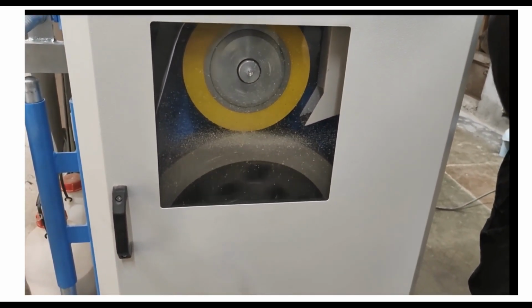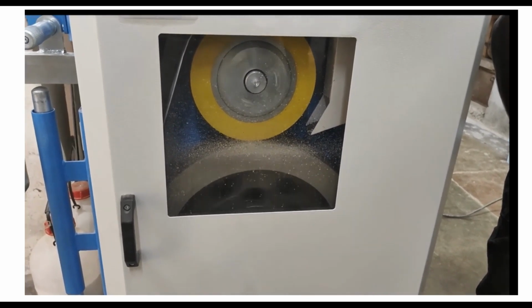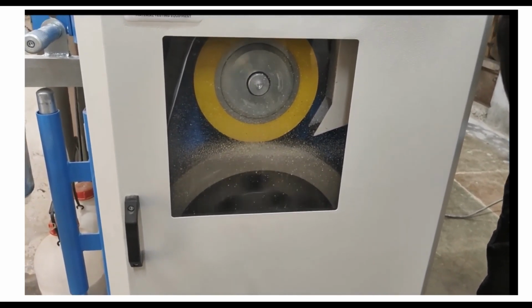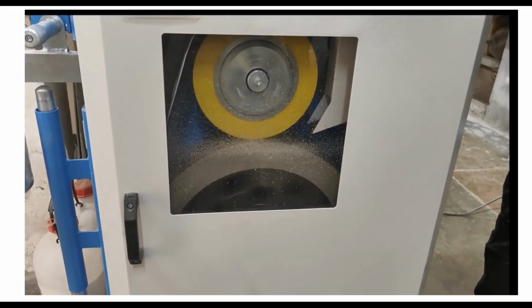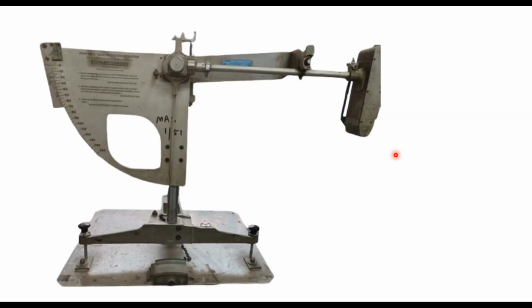After that, the machine is stopped. Samples are thoroughly cleaned by washing to remove any sand or other particles of stone. The machine is again operated for another 3 hours with release of emery powder instead of sand and water. And after 3 hours, the machine is stopped and samples are taken out and cleaned. In the second part of the experiment, these polished samples are tested for their friction value using a friction tester.